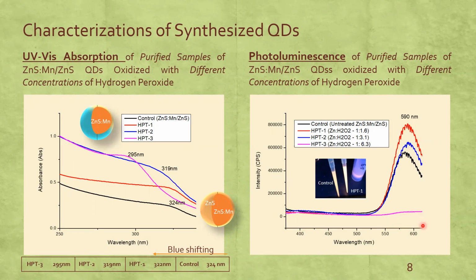It might have been oxidized so much that the outer surface is completely gone and the exposed manganese becomes unprotected for radiative relaxations to occur. Since it doesn't show fluorescence anymore, it is not a preferred model system, but we chose this sample to study XPS since the effect might be most pronounced on that one.